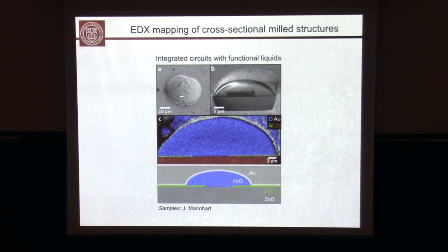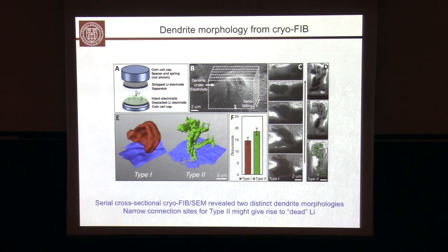So in this particular case, it's work we are doing with Jochen Mannhart at the MPI in Stuttgart, who is envisioning field effect transistors with integrated liquids. And there's been quite a bit of work in the condensed matter field using ionic gating for doping of systems. Here they have created integrated structures that include liquids. So imagine your phone might include liquids at some point. But in any case, here I want to just demonstrate we can create cross-sections, we can get pictures of the chemical distribution across these liquid-solid interfaces. So down here is an oxide, and right here is an aqueous phase. So you immediately see the impact that you could have for batteries. That's where all the processes that destroy your lithium metal batteries happen. And certainly, that's what we've tried to understand.